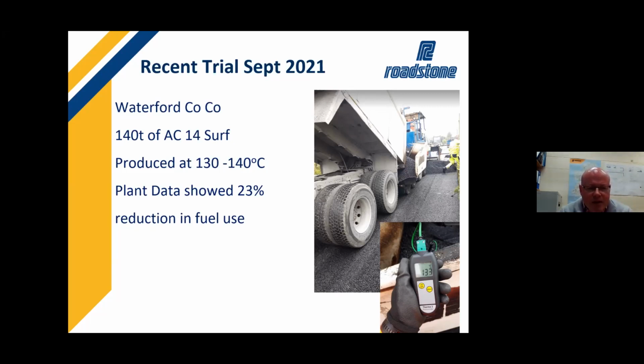The plant data for that day, we analysed to see what the fuel use was like. So compared to other materials that day and in the previous couple of days, we did see about a 23% reduction in fuel use at that point in time. And that would match with what we've seen across the industry. They would say 15 to 25% is what they have noted in the past can be achieved when using these products. It's very interesting to see that we landed right where we were told we would be.